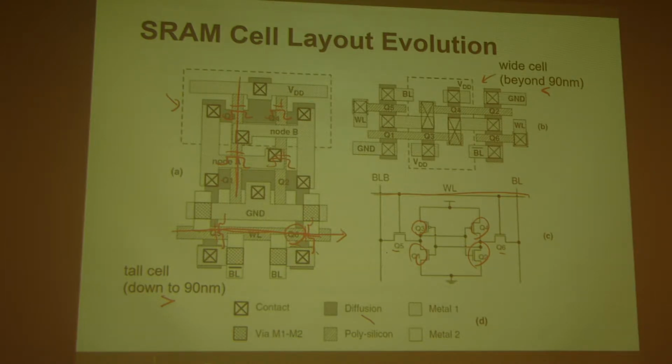So underneath the poly is also diffused? No. Under the poly, no. Under the poly, the channel region is your substrate, N-well, for example, for the PMOS. And you only dope the source and drain region by the self-aligned process. You use the polygate as a mask to dope source and drain. So underneath the polygate is protected, and you don't have dopant. But of course, later you do the annealing and then the dopant will naturally diffuse. So that's why you have the overlap between your gate and the source and the drain.